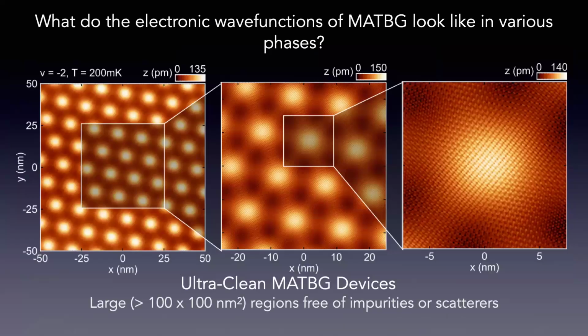So again, as I like to emphasize, we work very hard, we make very clean samples, and this turns out to be key. There's no other way to solve this puzzle unless you make samples that are pristine. I think this is sample number 250, I'm not joking. And what you see is, on the finest scale, you can see the atomic lattice of graphene, and here actually you see other things that I'll get to. And you go out to this large 50 by 50 nanometer area, which may not seem like a lot. This is like 100,000 atoms there. But there is not a single atom out of place and not a single adsorbate. Which is kind of crazy. I never thought this was possible.